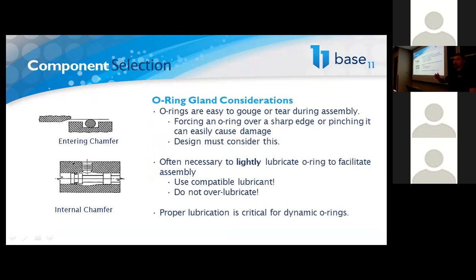So running an O-ring over threads can sometimes damage the O-ring. The other thing that can easily damage an O-ring is if you've got one part with an O-ring in it that's being inserted into a bore. If there's a sharp edge that's going to be scraping past that O-ring, then it's going to have a high chance of damaging it. So if you look at the figure on the top, you can see that they've added a nice, generous lead-in chamfer on the mating part so that they avoid gouging the O-ring.